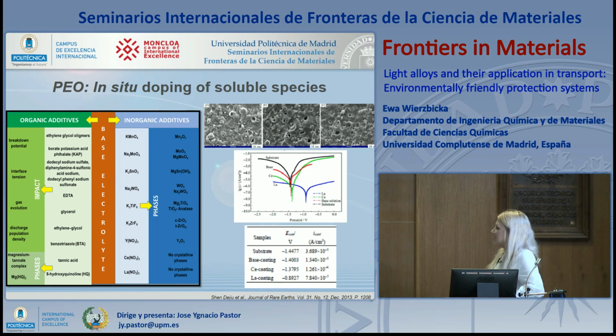There is also the possibility to add some soluble species into the electrolyte. Then they can be organic or inorganic as well. By using some organic additives, we will affect mostly the PEO process, and this way we will change, for instance, gas evolution or discharge population density. And by introduction of some inorganic additives, we can introduce to the coatings more resistive species